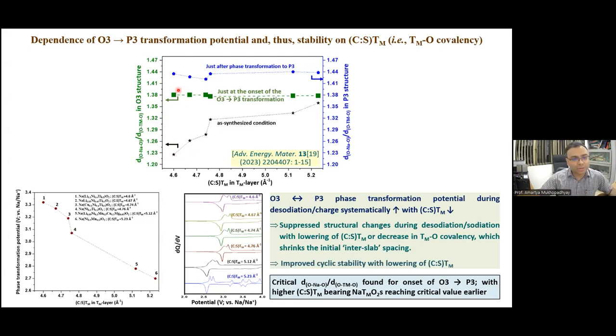So that's why having a low charge to size ratio in the transition metal slab is not only helpful for improving the water stability, but also very helpful for improving the cyclic stability of these layered transition metal oxides.